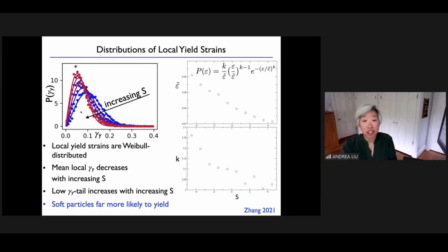So we then looked at the yield strain distribution for particles of different softness. The softness here is given by the color. Very high softness particles are red, low softness particles are blue. And what you see is that this yield strain distribution, because it is an extreme value, a minimum, is Weibull distributed, has the form of an extreme value distribution, with a mean which decreases with increasing softness. So the softer it is, the lower the mean local yield stress, and also an exponent that depends on softness. So the low tail gets bigger as you increase the softness.